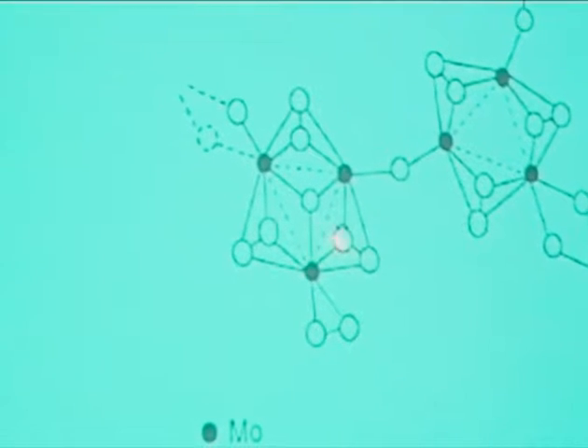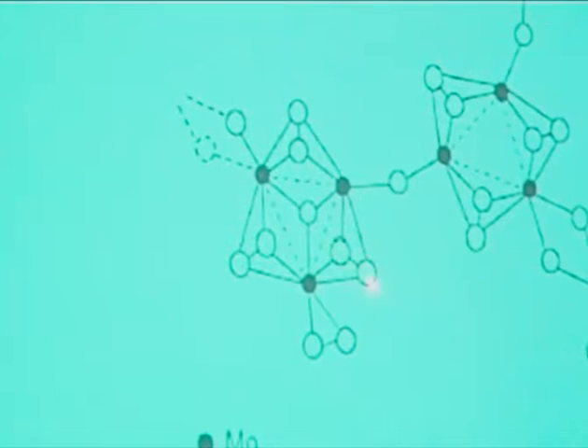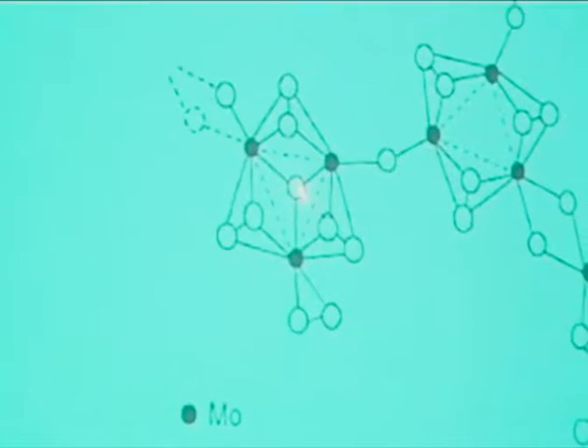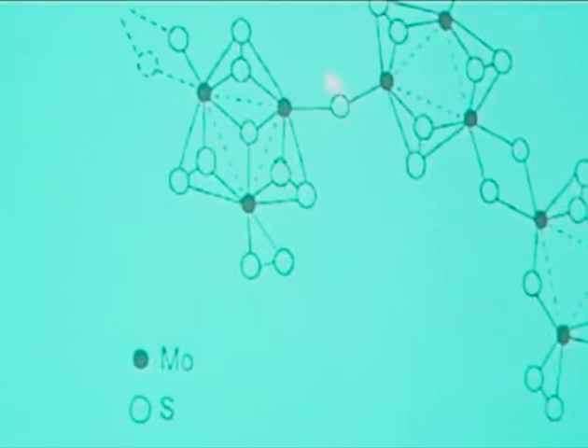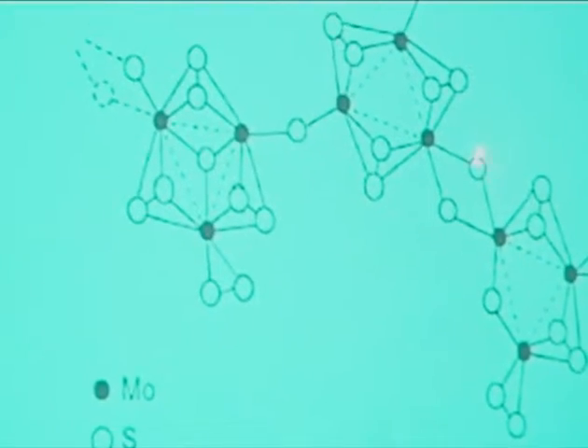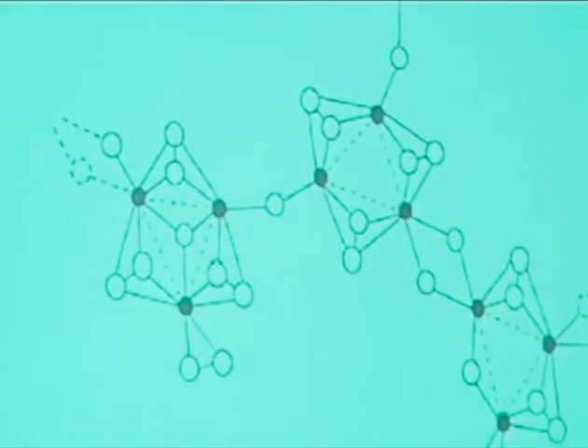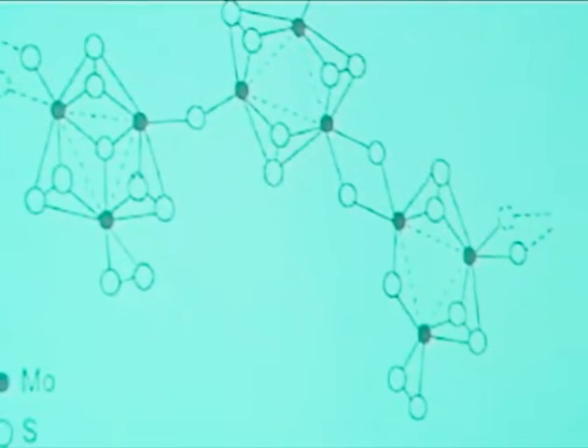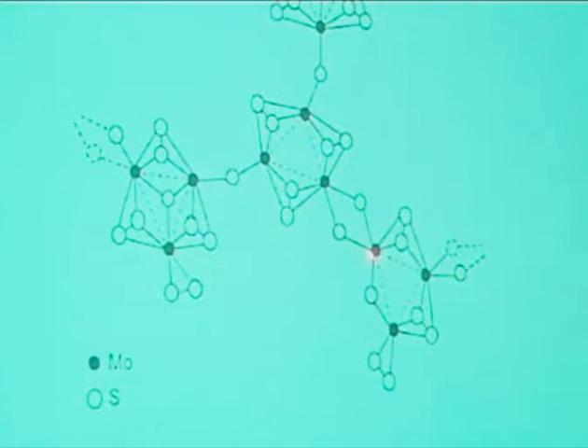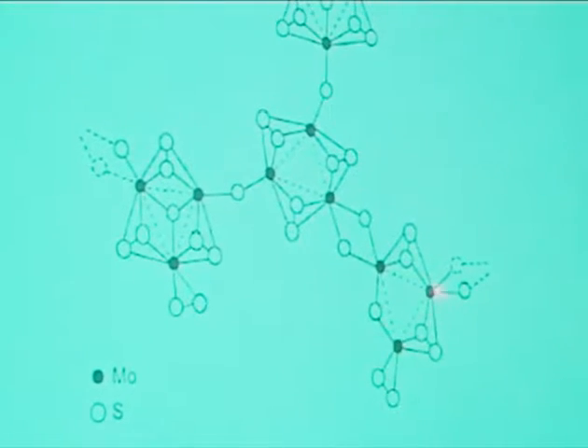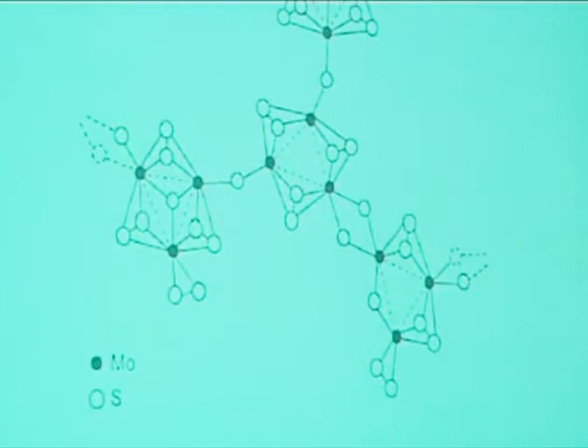You have probably triangles of molybdenum. The infrared suggests that strongly, with disulfur bridge, so S2 2-. And you have a sulfur apical in between three, and then you have bridges of sulfur or disulfur bridges. And this is why you can have everything. But in principle, you have the molybdenum-sulfur distance and the molybdenum-molybdenum distance, and the molybdenum-molybdenum distance is on the short side.